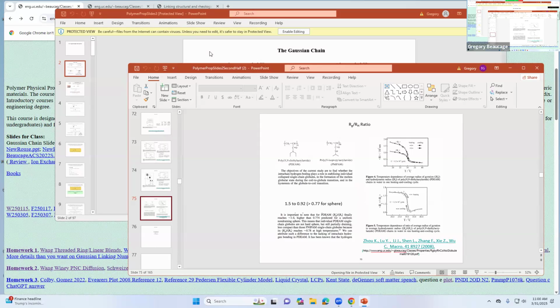So the exact numbers people spend a lot of time worrying about, but if the system's polydisperse, then Rg is just looking at the largest things. So yeah, it's a larger number because you're looking at the boulders on the beach. So basically there's a little bit of fudging on this because nothing is going to be totally monodisperse. You have to be careful about how you throw these things around because they're averages and what moment is the average. A harmonic mean's weighted towards the small things because 1 over a small number is a big number. So if you average the 1 overs, the small ones dominate. So Rh should be smaller than Rg by that argument.